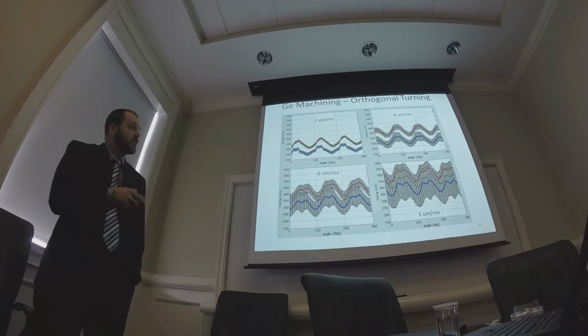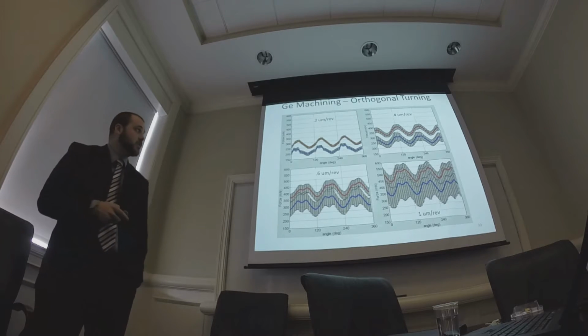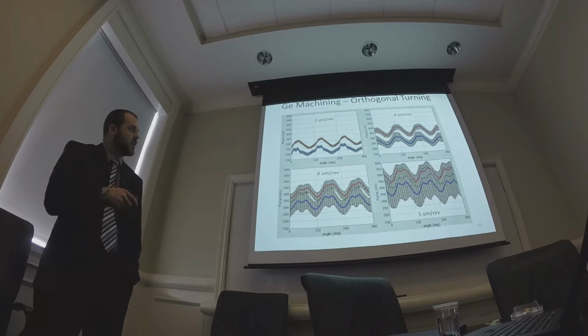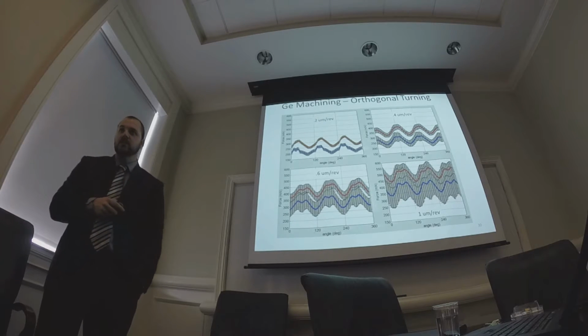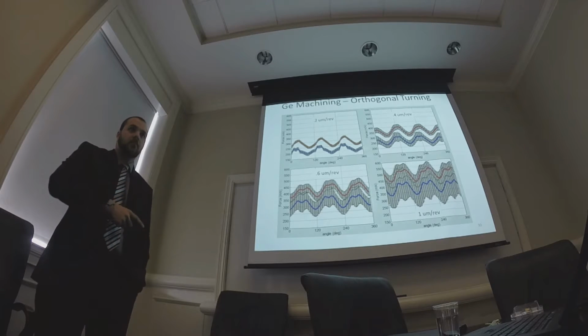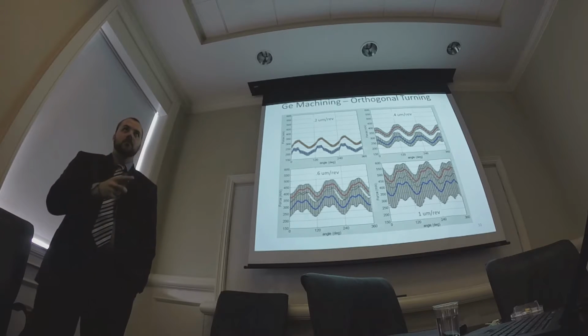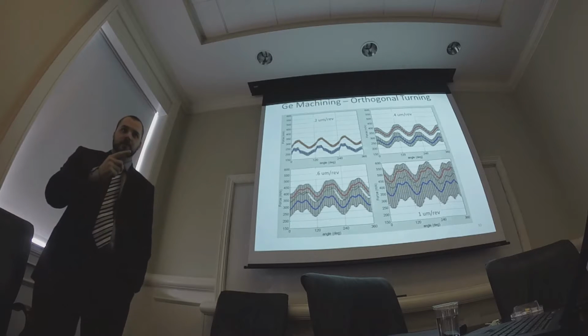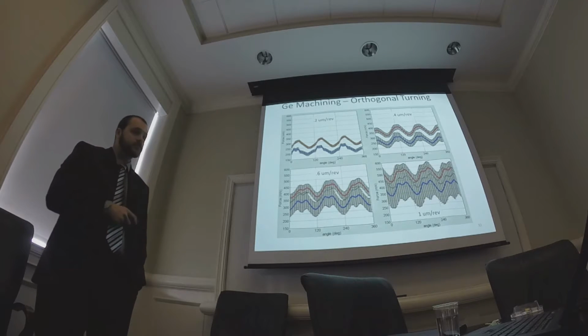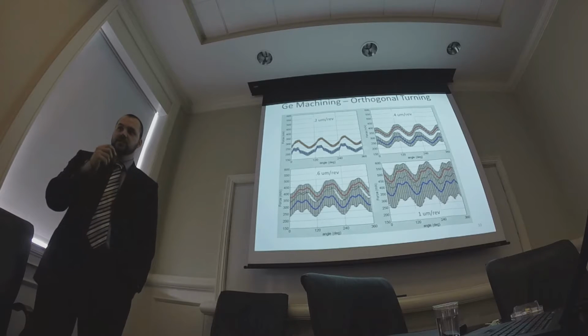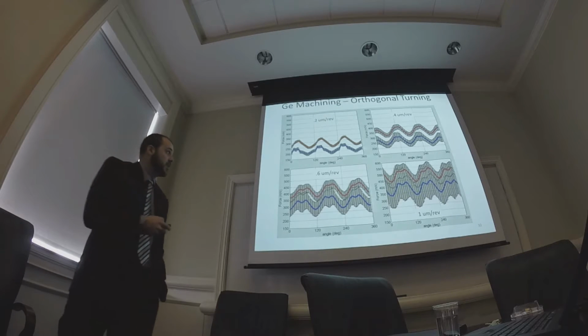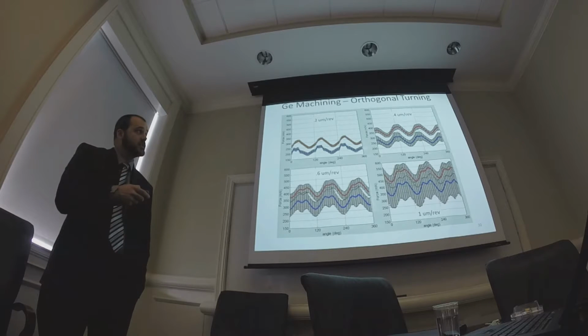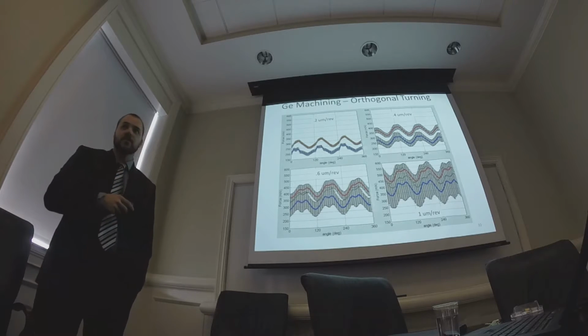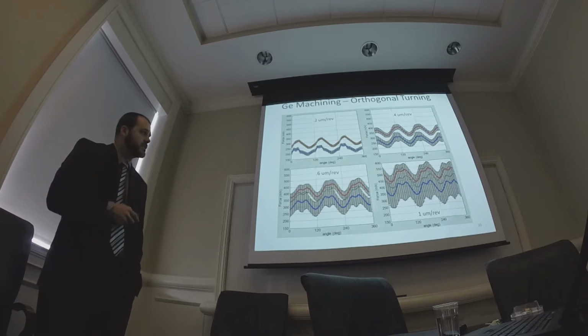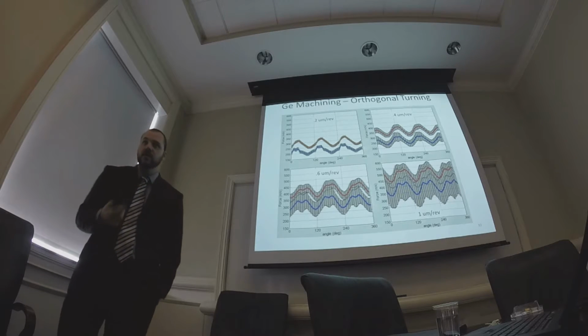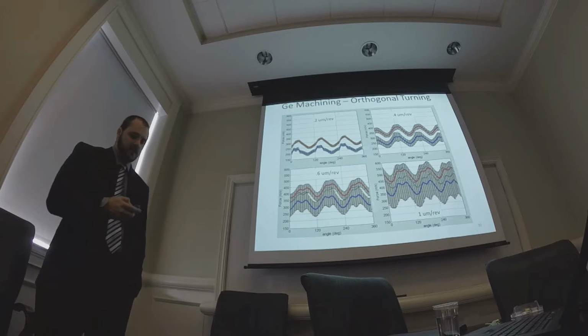Then 4 different chip thicknesses, just looking at the effects of crystal orientation. This feature right here is something Horiuchi mentioned as well, where at the best fracture-free region, there's this tiny little band right in the middle that will actually start to fracture just before the surrounding area does. That's what we're seeing here - this drop in force starting to occur in that 400 to 500 nanometer range. That's very interesting and corresponded with results we've seen in literature.